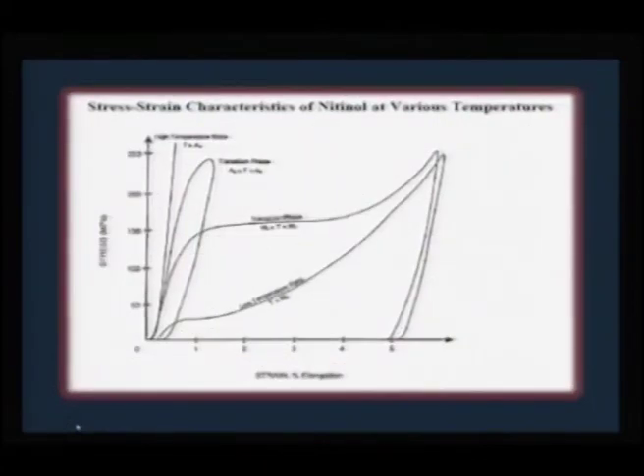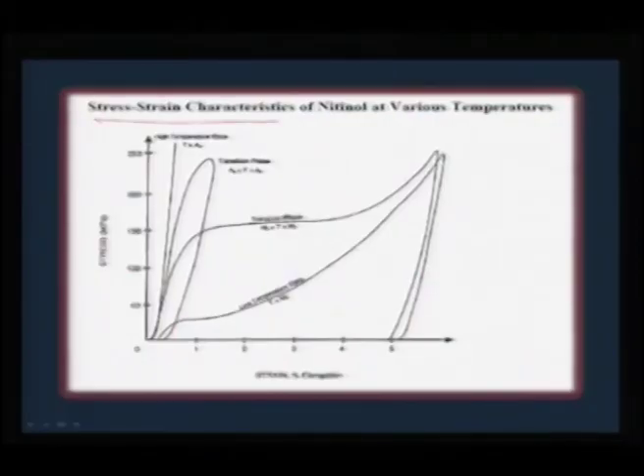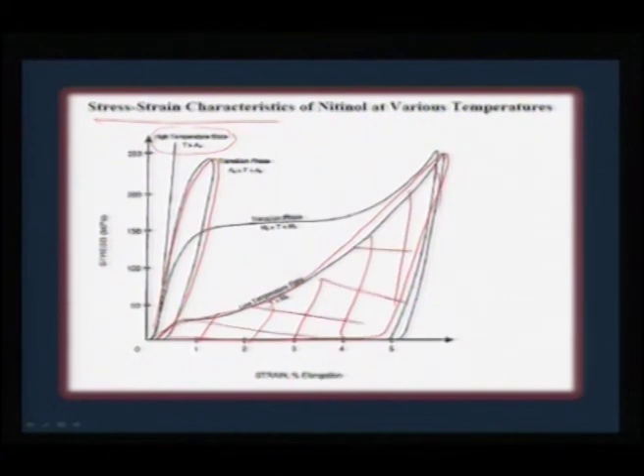best ones. So, just to sum up why nitinol is good, if you plot stress versus strain, in different regimes this is how it works. In the high temperature state, if you take it beyond the transformation temperature, it does not come back, it is irreversible. Otherwise, within the transition phases, you see a clear hysteresis produced at high temperature, and similarly at low temperature you can see another hysteresis.